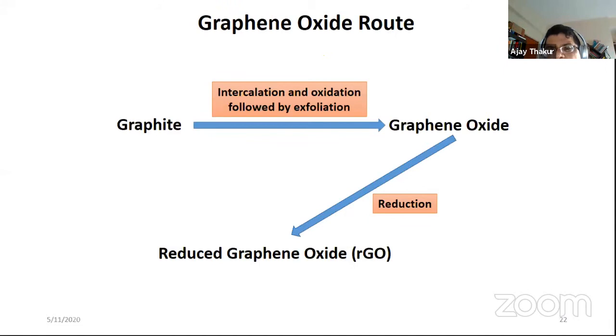So therefore, a graphene oxide essentially is a carbon sheet like graphene, where a number of carbon atoms have oxygen-containing functional groups in general, and some of them may also have hydrogen-containing functional groups. Okay, and the reduction of this essentially means that what you are trying to do is break the bonds with these functional groups. So you would try to remove these functional groups which are attached to the carbon layer, and then at the end of the reduction process, you reach reduced graphene oxide.